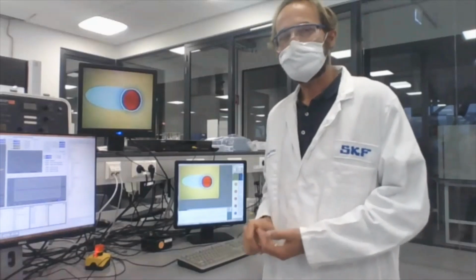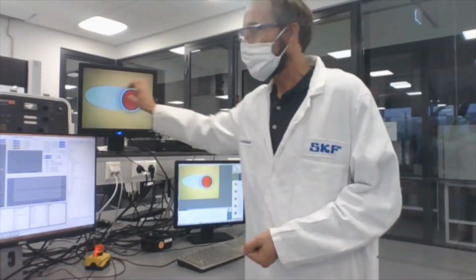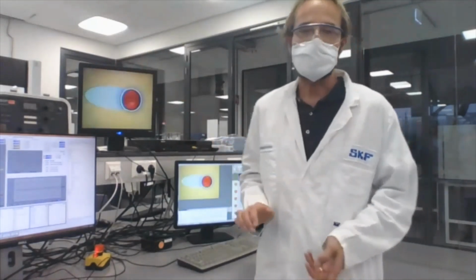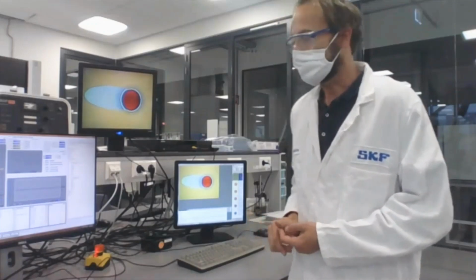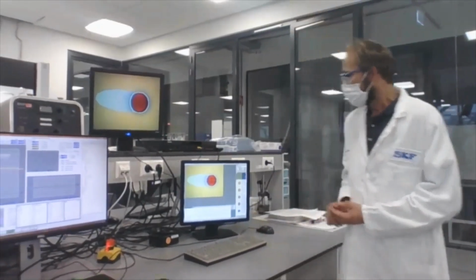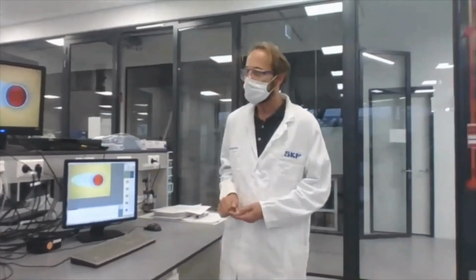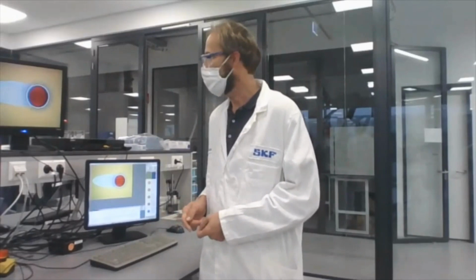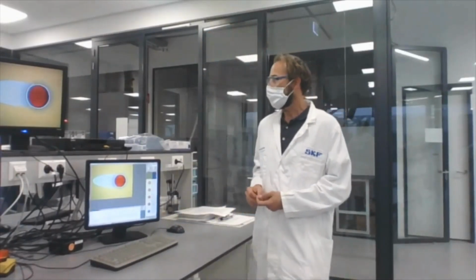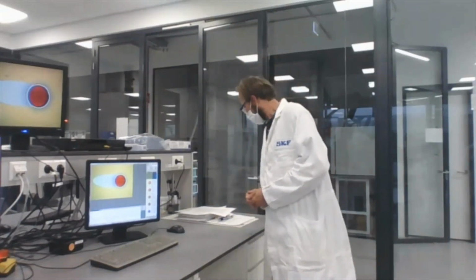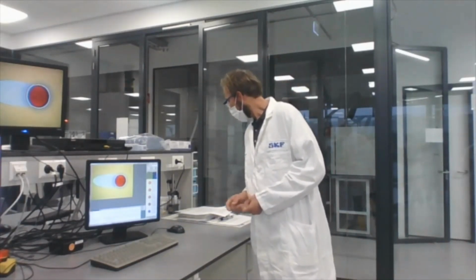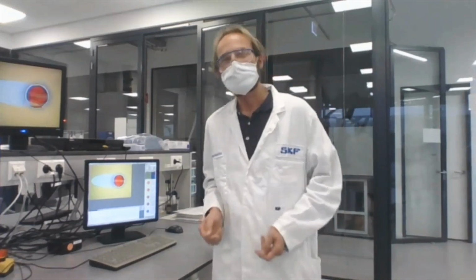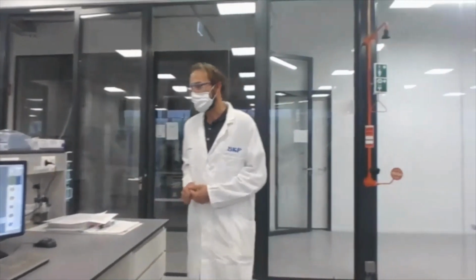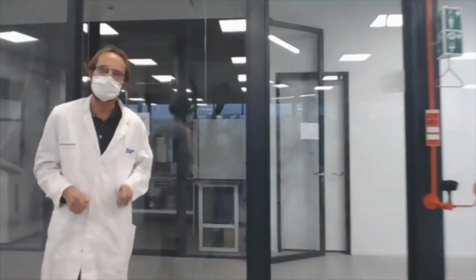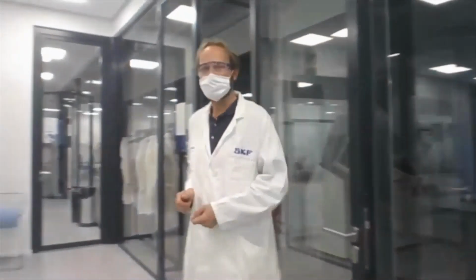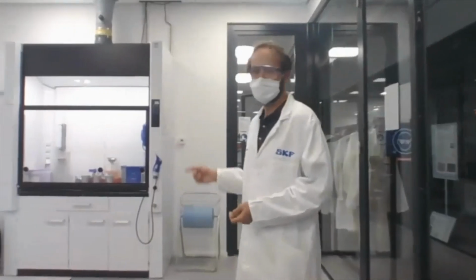So the water in the oil does not have an effect on the actual film thickness, but it does leave a trail of water. So if you then stop the bearing and it's standing still, that's when you can get corrosion, which is called standstill corrosion. So in short, the WAM can be used to evaluate the lubrication performance of lubricants that are contaminated. Next, we are going to see a similar rig, which is also a ball and disc machine, that is used to look at the tribological performance in terms of friction and surface interaction from additives, and that will be shown by my colleague there, Nicola.